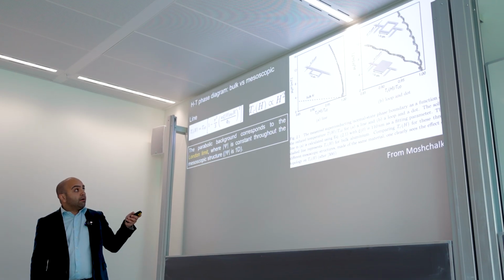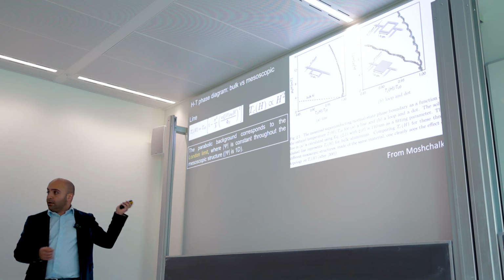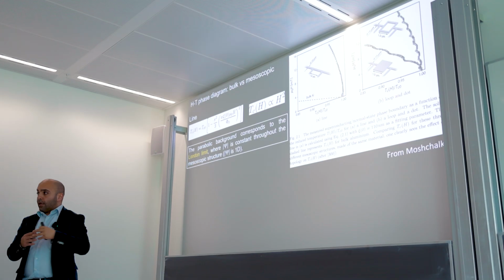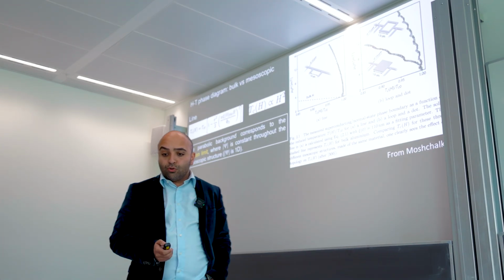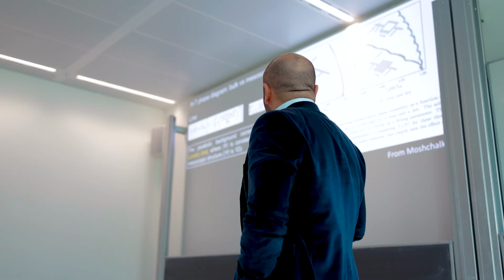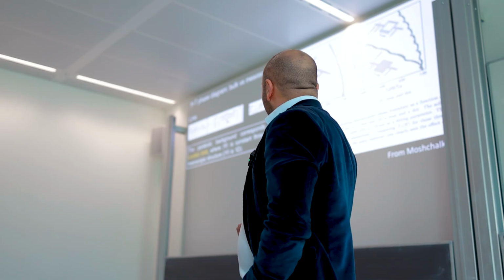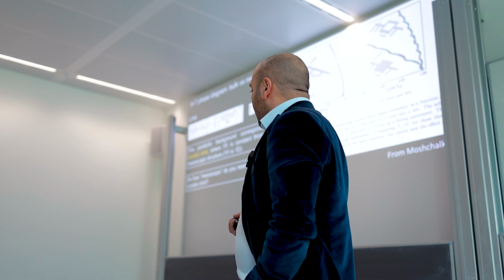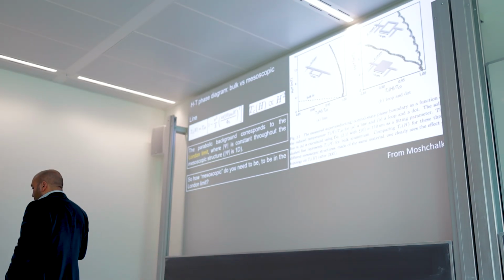And so there is a bit of a crossover. You see here there's a tiny wire, and this is the loop. You see it has the Little-Parks oscillation we talked about on top of this background. And here we have a disk, which is somewhere in between. So there's actually a crossover going from a 1D superconductor, that's what the London limit is, to a 2D superconductor. And in 1D you end up having a higher critical field because of confinement effects. I'll come back to that in a second, but the reason is that you actually save a lot of energy when you go into this 1D limit.